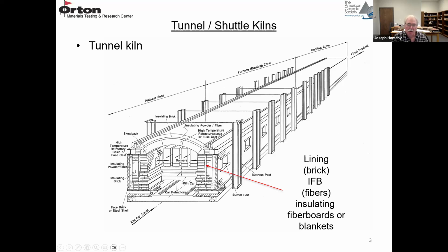And there's no issues here with corrosion or thermal shock. So these are going to be lined with an insulating firebrick, an IFB, or some type of fiber lining. It could be fiber boards or it could be fiber blankets. The fiber blankets can be folded to create different thicknesses and attached to the wall. So IFBs or different types of fibers.